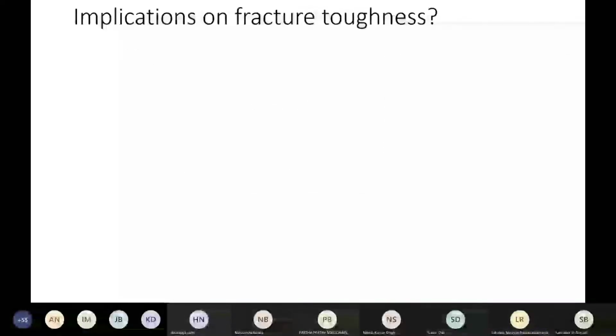Now, what are the implications of these shear bands on fracture toughness? Fracture toughness, as you know, is a property that is extremely related to plasticity. If a material has the ability to take more plastic strain, it will have higher fracture toughness. That is what we learned, because we talk about the area under the stress strain curve till failure, which means that there's a large scope for plasticity to play a role in fracture toughness.